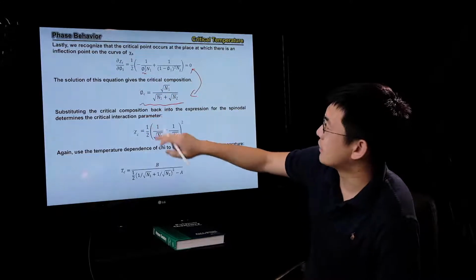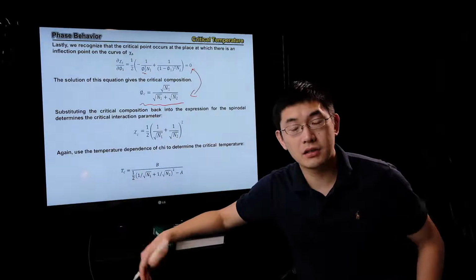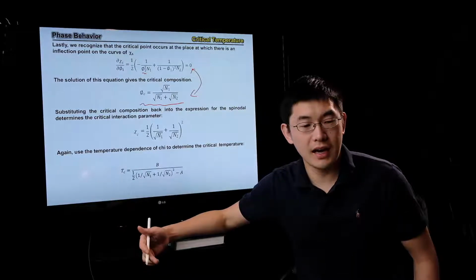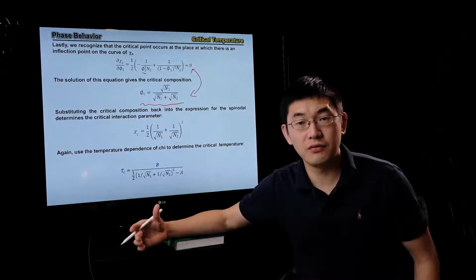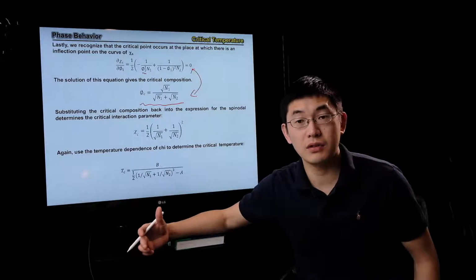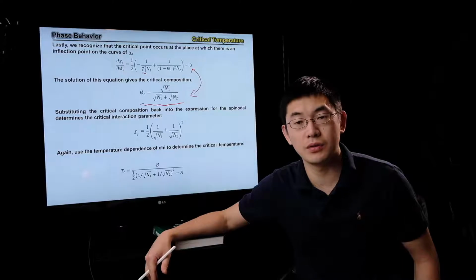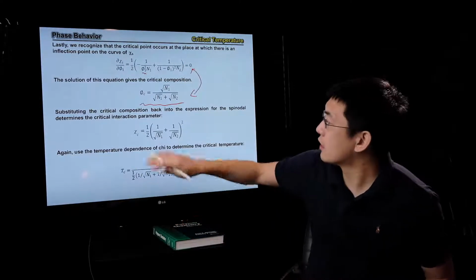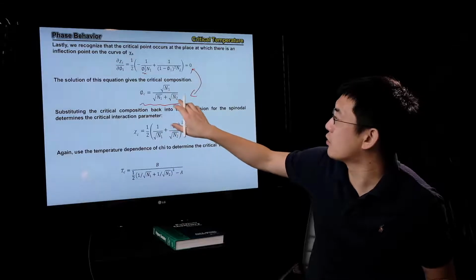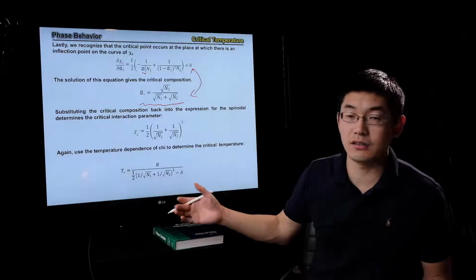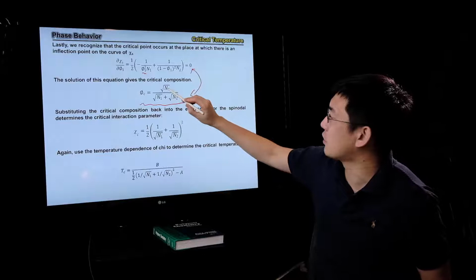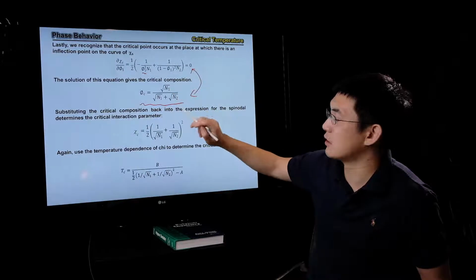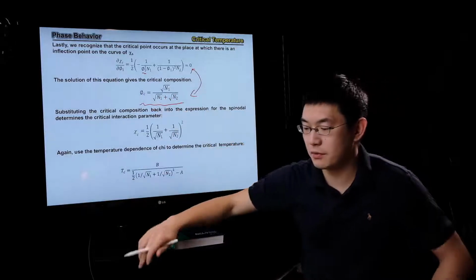And this would be the conclusion. If you think about what I just mentioned in the lattice theory, phi c is 0.5, right? It's usually symmetric, and at the critical temperature, your phi c is a 50-50 mixture at the middle of the curve. You can apply n1, n2 equals 1, which is the case of lattice theory. Then you can see the root of 1 is 1, and at the bottom you have 1 plus 1 equals 2. So phi c is 0.5.